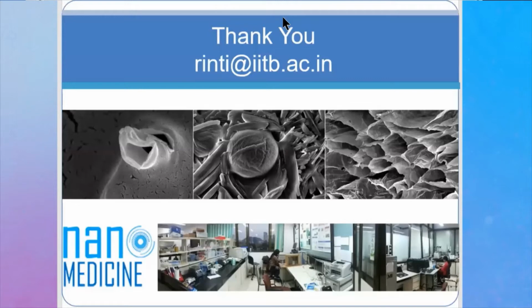How will you control endosomal escape? So there are various strategies that can be built into the biomaterial carrier for endosomal escape. Some of which are essentially determined by change of phase as soon as the endosome is reached. With the change in pH, there's a change of phase of the biomaterial, and one example being lamellar to inverted hexagonal. So when that happens, you get an inside out conformation, and you come out of the endosome and into the cytoplasm.